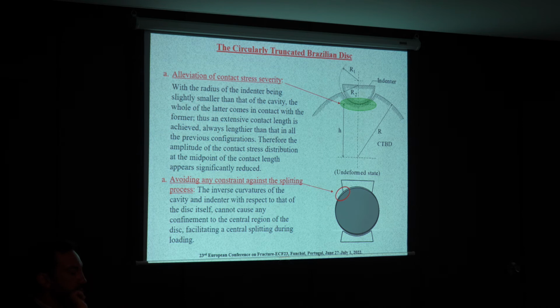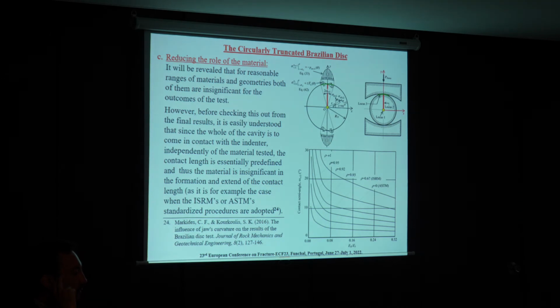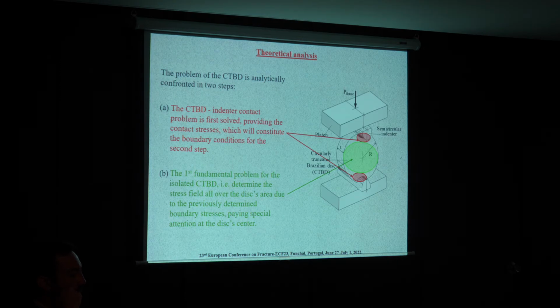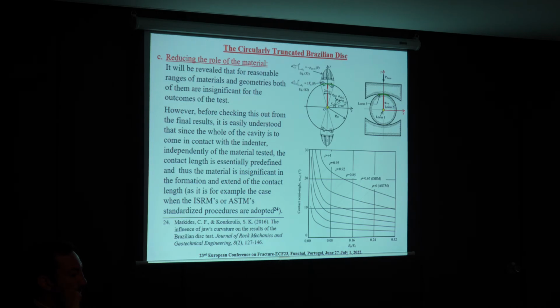Also, since the curvature is inverse, we have no restrictions on the tendency of the material to move apart, so we do not restrict the tensile components. And finally, what is more important, the results obtained from this configuration are material independent. Perhaps it sounds strange. We all know that stresses do not depend on the material, or this is what we think. But since both the platens and the material are of specific stiffness, the contact arc developed during the execution of the Brazilian disc test increases gradually, which means that the results obtained finally depend on the relative stiffness of the material. And this is of huge importance. It is not 2 or 3 or 5%. It may obtain values up to 30% different.